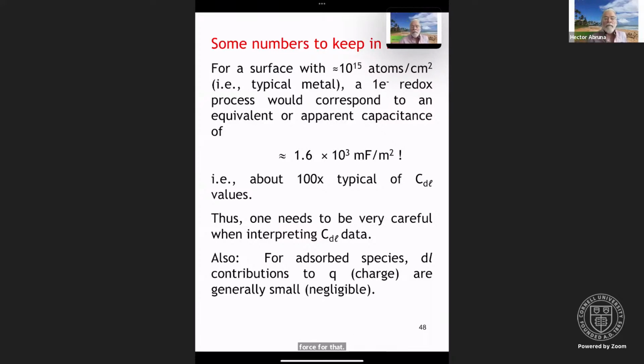A little bit more on numbers. For a surface, as we mentioned, 10 to the 15th atoms, which is typical of a metal, a 1 electron redox process corresponds to an equivalent capacitance of 1.6 times 10 to the 3rd millifarads per meter squared. And what does that mean? Basically, this is about 100 times the typical double layer capacitance of your electrode. That means if you're doing studies where you're looking at the double layer of your interface, you have to be really, really careful if you have any process that involves charge transfer, because it can overwhelm the capacitance that you measure. For adsorbed species, the contributions just from double layer charge are small, but faradaic processes, as you saw, are enormously important.